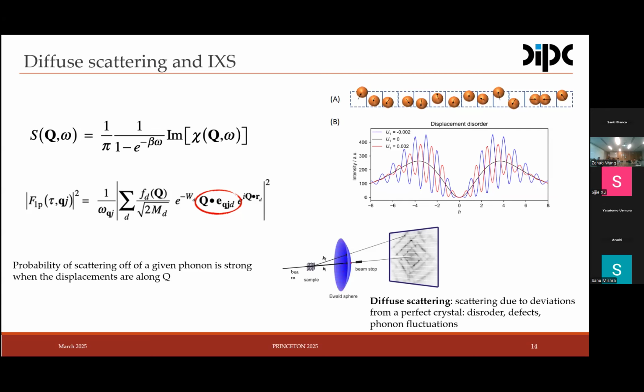Diffuse scattering is an energy integrated experiment. So we see some signal, some blob of intensity in the diffraction pattern. It may come from an elastic process or from some inelastic phonon mediated origin. For that, we take the sample to an inelastic X-ray scattering beamline, usually at SPring-8, Japan, or in Chicago. The idea is just to resolve the energy spectrum in the scattering experiment. If this diffuse scattering comes from phonons, we will see some anomalies in the phonon spectrum, or if it comes from some static elastic signal, then it shows up at zero energy loss.